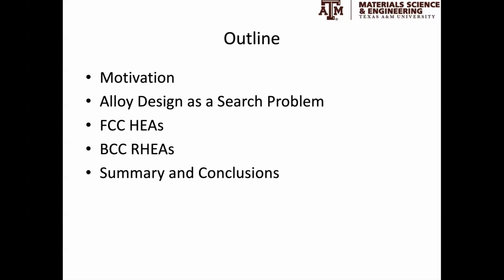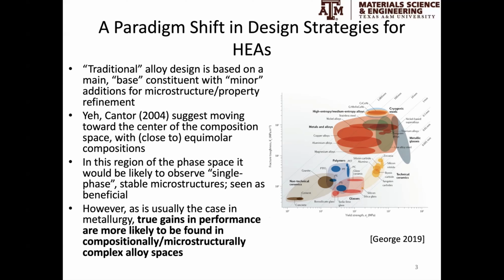In 2004, two different works independently suggested moving towards the center of the composition space with close to equimolar compositions. In this region, it was argued that it was going to be very likely to observe single phase stable microstructures because of potential configurational entropy gains. Having a single phase microstructure was seen as beneficial. For many years, looking for equimolar alloys in metallic systems was seen as the guiding principle in many, not all, of the efforts to explore the high entropy alloy space.